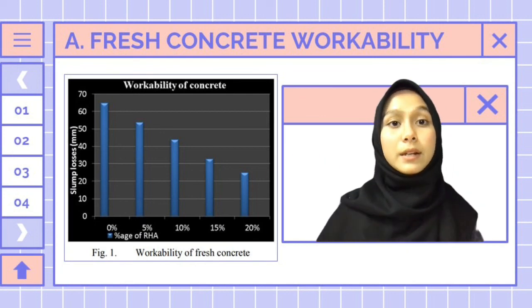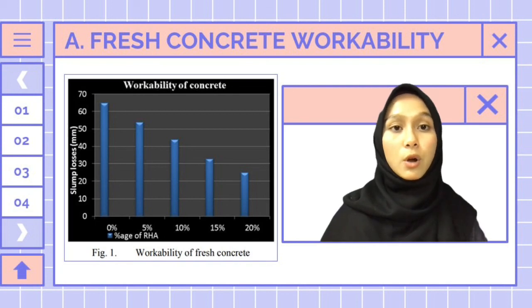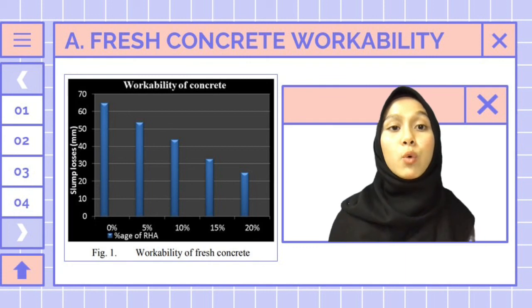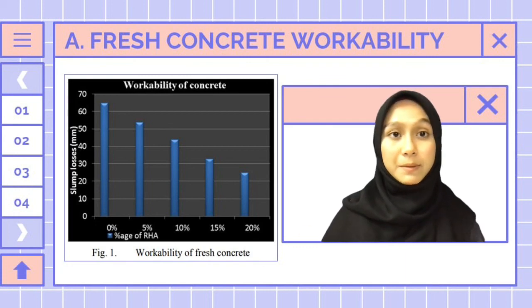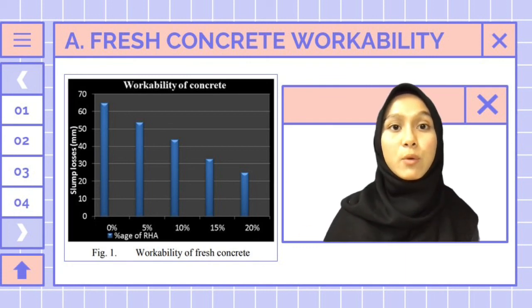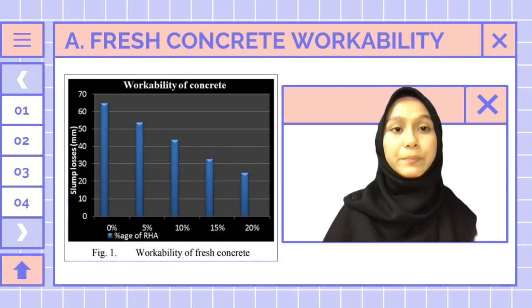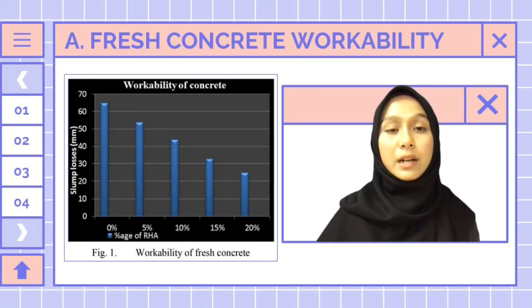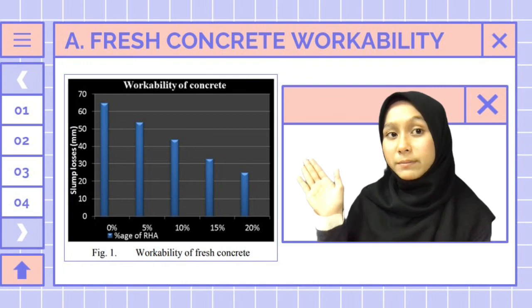Beside me, the graph shows that the maximum flow of concrete was at 65 mm while using 0% RHA as cement substituent material in the concrete, and the minimum value of the workability was at 25 mm at 20% RHA by weight. It was concluded that the flow of fresh concrete decreases with an increase in the amount of RHA in the concrete. The experimental results are shown in figure 1.